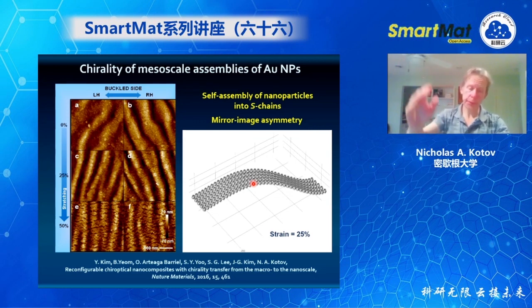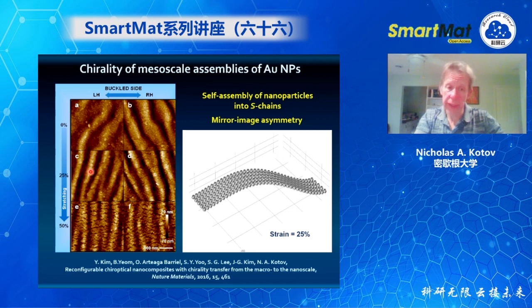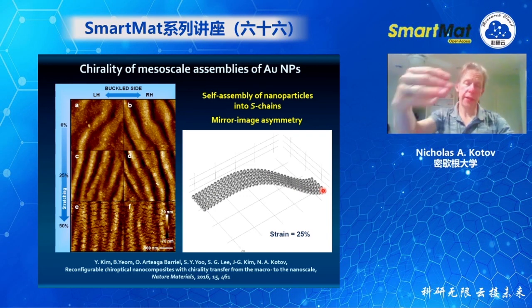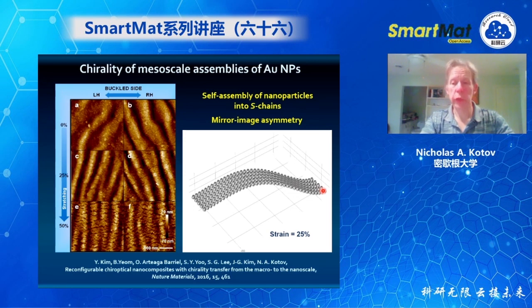First, we have the wrinkles, which are not absolutely organized as in the work of Andreas Fery, but they have their periodicity. What's even more important for the optical properties is that the nanoparticles here are organized into chains. And these chains have a three-dimensional structure. And if we look at the mirror, for instance, here, these chains become mirror asymmetric, or chiral.